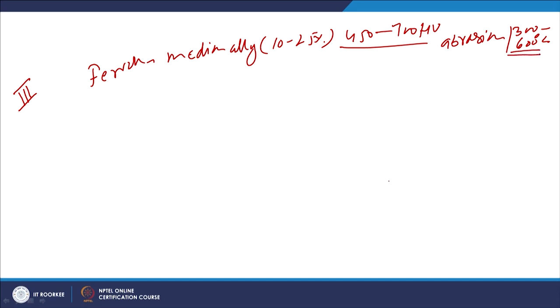So these kinds of conditions exist in the hot rolling mills. Since the hot rolling mills experience abrasion under high adhesion as well as abrasion at a high temperature, in order to resist the material loss by wear under such conditions, category 3 ferrous materials are used for surfacing so that the tribological life can be enhanced and the material loss from the functional surfaces can be reduced.